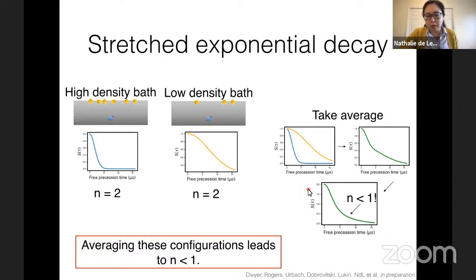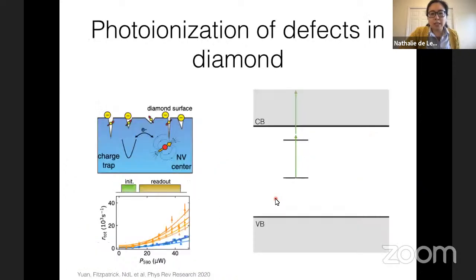So basically, one question is: is it possible that the NV center is looking at some configurational averaging of the surface spin bath? Separately, in my group we were working a lot on photoionization dynamics of NV centers in diamond, where if you just shine green light on the NV long enough, you get this 2-photon ionization into the conduction band, and it switches charge state to NV0. We knew we could monkey around with this photoionization quite a bit. So it's a natural question: is it possible that these surface spins are also getting photoionized, and that scrambles their positions?